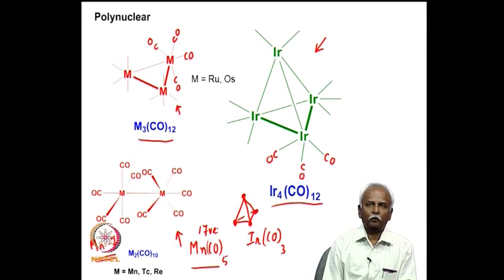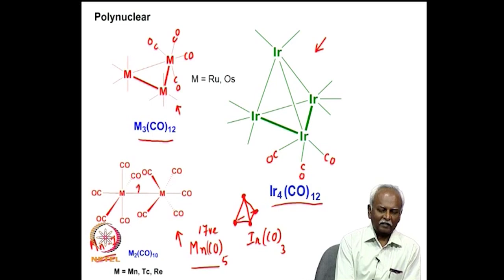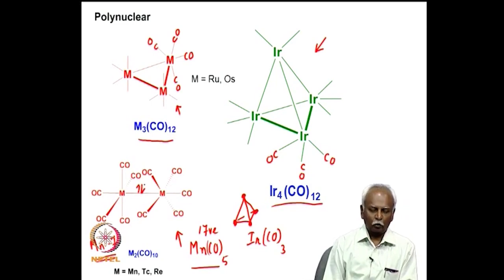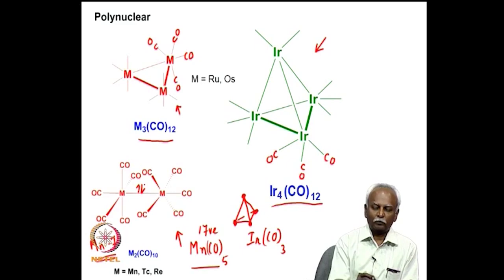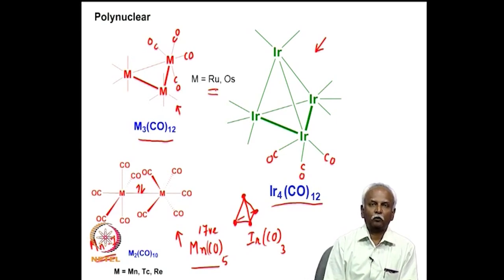Now, this one electron, if it can be shared between the two manganese atoms, then each manganese can end up with a valence electron count of 18. So, that sharing of that one electron between the two manganese atoms results in the formation of a bond between the two manganese atoms, and that is what you have in each one of these cases. Either it forms 2 bonds, as in the case of ruthenium, in order to achieve a valence electron count of 18, and in the case of iridium, it has to form 3 bonds in order to achieve a valence electron count of 18. So, the formation of a polynuclear species with a metal-metal bond is primarily determined by the electron count.